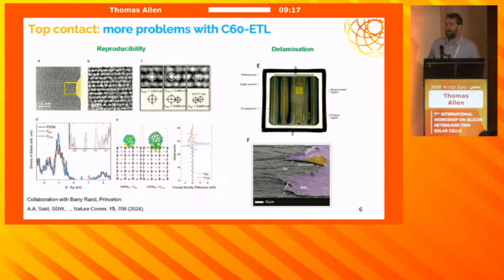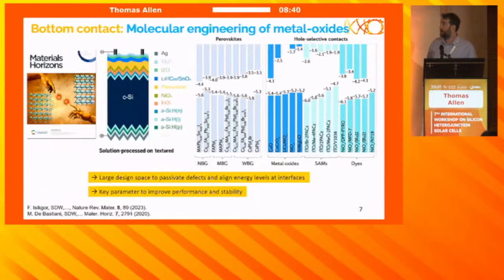And also, depending perhaps on many factors relating to the encapsulation, you can very easily have delamination of the C60 interface because it's so chemically inert. There's very weak binding to the underlying and overlying layers of the perovskite, and you can see a lot of delamination depending on your process and depending on your lamination material. So C60 is causing a lot of problems. And in my opinion, they haven't in any way all been solved, and that's where I think a lot of the remaining work will come from in the device, at least in terms of efficiency, let alone stability.